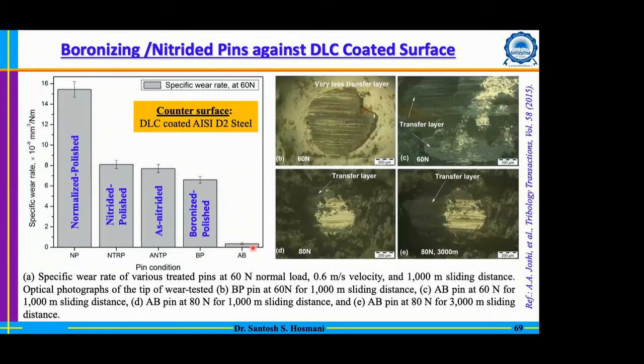That means if you are using a DLC coating, better not to polish your boronized surface, better to have some roughness there. That roughness is helping us to accumulate the transfer layer, and that is actually a helpful advantage. So better not to polish the boronized surface. That is what this particular slide helps us to understand.